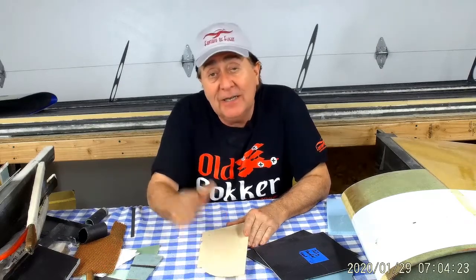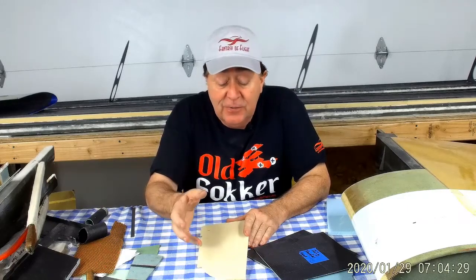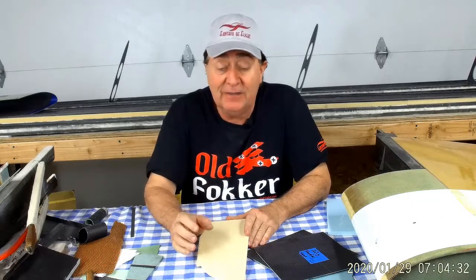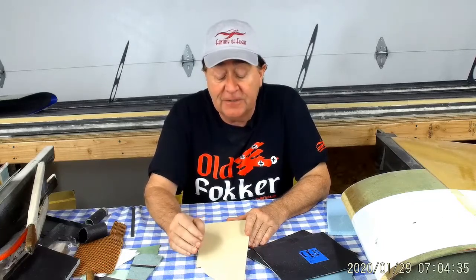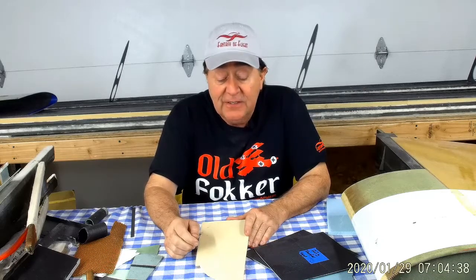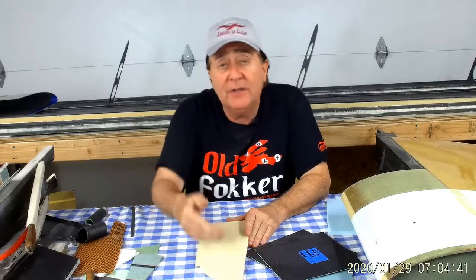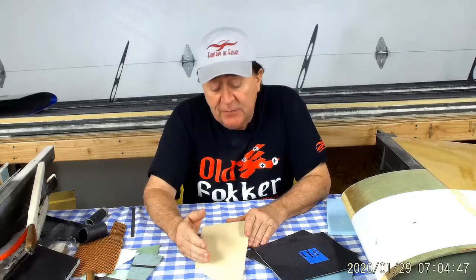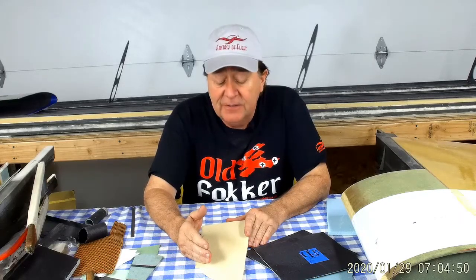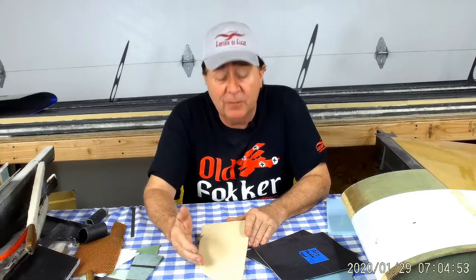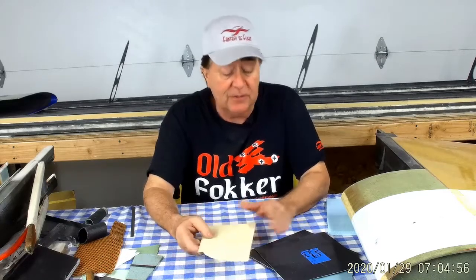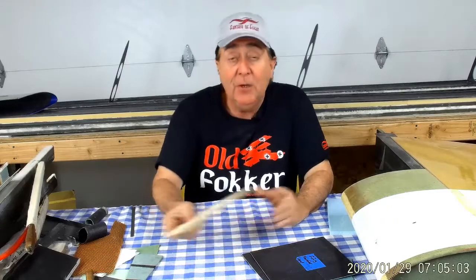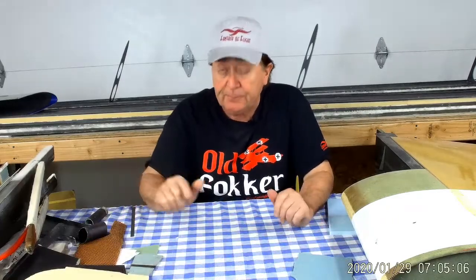I used this technique on my original wing to fill the white bead foam that is on the inside of the D-tube, because a lot of resin can go into that thing. There are a lot of voids and so forth to fill. It's very significant, and I got varying results on this. And I thought, geez, I'm filling the cells. And I know that the lightweight microballoon filler that I put on here is about the same density as the foam, a little bit higher, but it's a lot lighter than resin. So where's the weight coming from? What's going on? I had to look at this a little bit in order to determine why all this extra work that I was doing to fill the surface and then do the layup was not paying off in reduced weight. Let me show you what happened here.